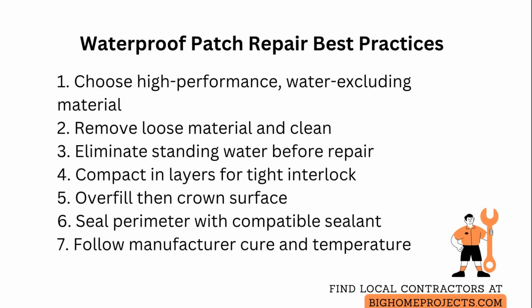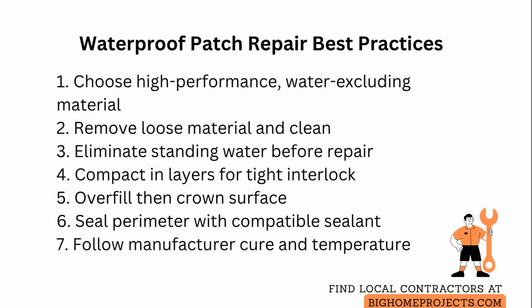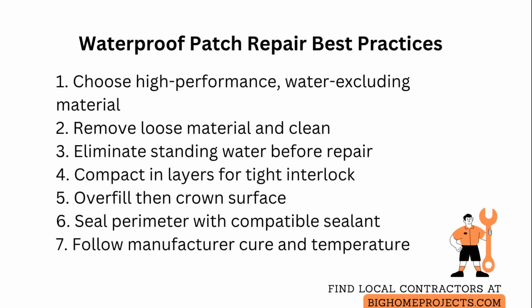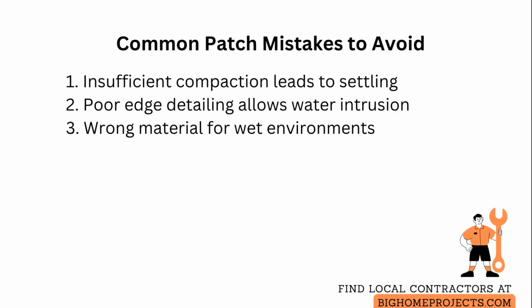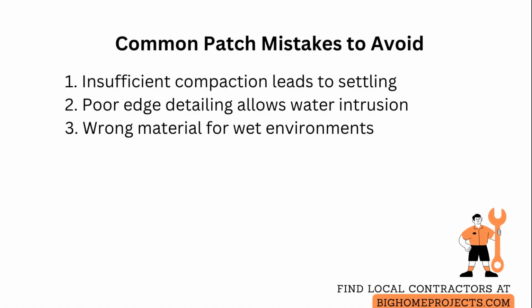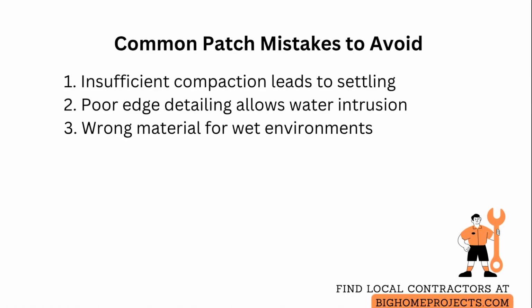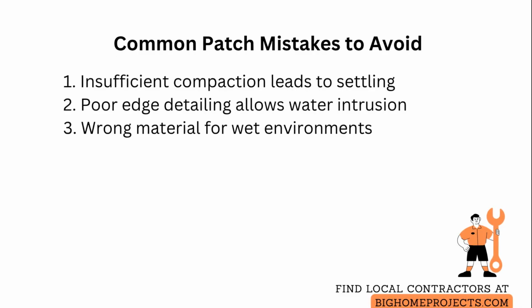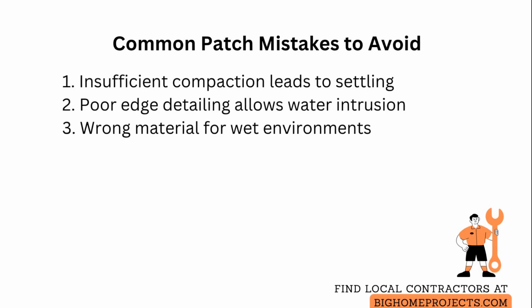Allow proper cure time before exposing to traffic or heavy water, and follow manufacturer temperature and moisture cure guidance to achieve designed performance. 3 common issues are insufficient compaction, poor edge detailing, and using the wrong material for wet environments. If compaction is inadequate, the patch will settle and open pathways for water, so rework in lifts with proper tamping until the material resists finger depression.